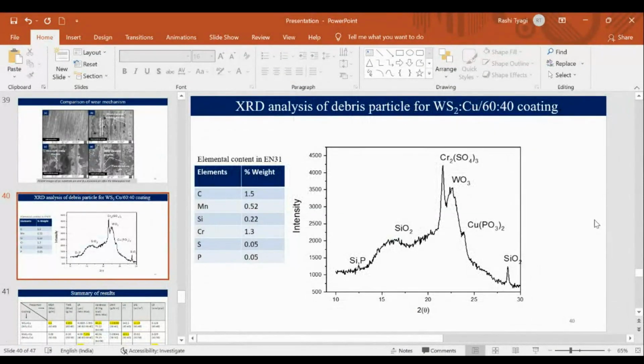As the material is removed, debris particles form. So we have done the XRD analysis of the debris particles, in which you can see the elements contained in the EN31 steel disc. The disc that we are using against the pin, as I showed you, is rotating against the pin. So this is the different composition of the disc material that you can see. In this XRD of the debris particles, you can see chromium sulfate in a high amount. So the maximum removal takes place from the disc as compared to the pin, which is what we want, because we want low removal from the pin in order to utilize a good coating. So we can say a good coating with excellent tribological properties is obtained by this process, as the removal is very little. That can be seen from this debris particle XRD.